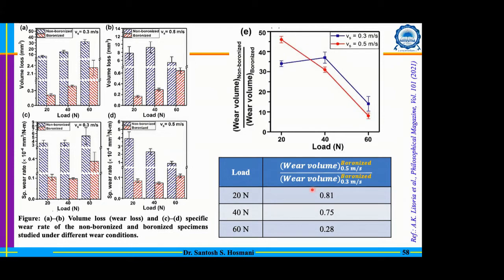That means, in fact, your material is behaving very well at a very high speed compared to that of the lower speed. And that is probably linked with the SRS. It is a strain rate sensitivity. That is what actually we expect. Obviously, the top graph is not really giving us good information about the boronized surface.